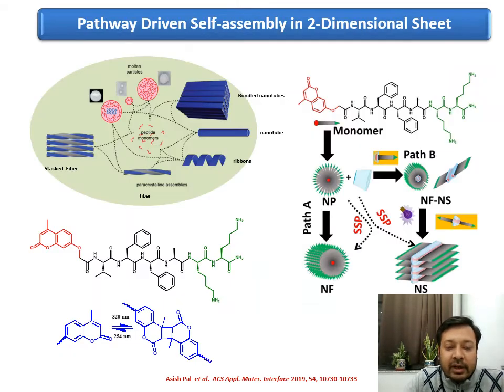And having done so, we also thought, can we really have it in 2 dimensions? And for that, what we have done is that for such kind of amyloid peptide amphiphile, at the N terminus, we put an interesting moiety called the coumarin moiety. Now, coumarin moiety has a very interesting reversible photo cycloaddition. They can form at 320 nanometer the cyclobutane adduct, which can be reversibly cleaved by 254 nanometer light.